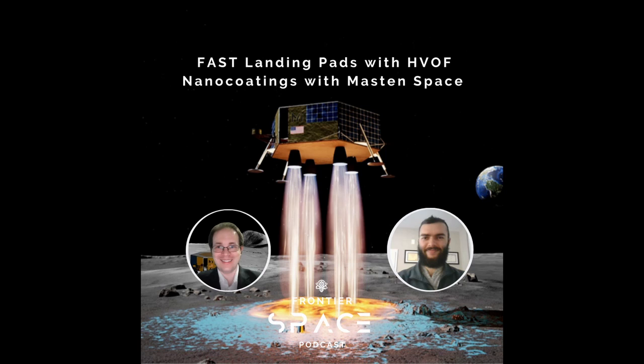So that was one set of experiments, and it was really, really cool because we found some stuff we weren't expecting, such as when we get particles that are impacting in very close time proximity to each other and very close distance proximity to each other, it changes the cratering dynamics on the surface, even for very small particles. So you can actually control and tune how much splash and disruption of the surface you get as you're deploying the landing pad to optimize the surface compression, the performance, and the interface layer. So you need to build an interface layer between the lunar regolith and the hard top coat of the landing pad, which takes the brunt of the thermal impact. And you do that by building up a graded layer of particles on the surface. And so that was one series of tests we did.